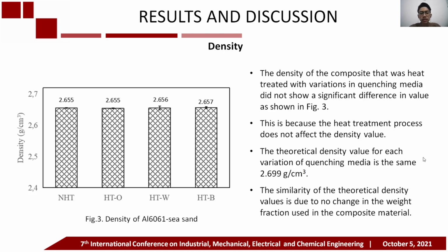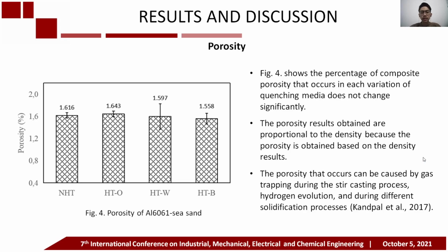And then the next discussion is results and discussion. First, I will talk about the density of the composite. The density of the composite that was heat treated with variation in quenching agents did not show a significant difference in value as shown in figure 3. This is because the heat treatment process does not affect the density value. The theoretical density value for each variation of quenching agent is the same, 2.699 grams per cc. The similarity of the theoretical density values is due to no change in the weight fraction used in the composite material.